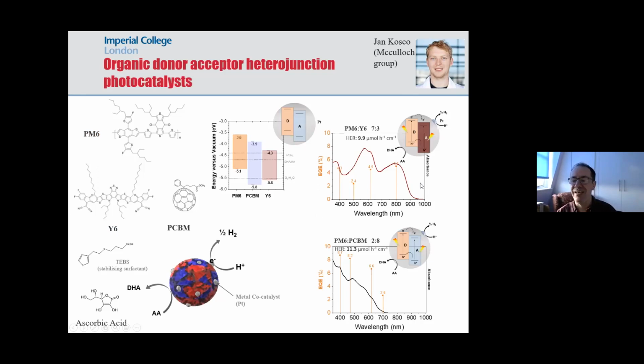Now, the efficiencies here are not the same as the efficiencies of solar cells. These quantum efficiencies are in the range of a few to up to 10%, not in the range of 80 to 90% we have in the solar cells. But these sorts of particle suspensions in water have a particular interest for low-cost hydrogen generation. Most of the cost analyses of how we could really imagine making cheap hydrogen involve some sort of suspension in water and shining light on it to generate hydrogen and oxygen or another oxidant. In this case, we're not oxidizing water, we're oxidizing ascorbic acid.